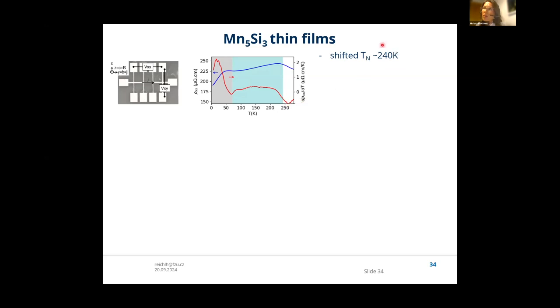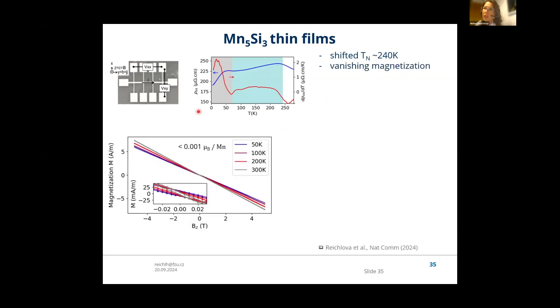So in our case, the Néel temperature is approximately 240 Kelvin, and it's paramagnetic above. In this temperature range, it's a collinear system, and in the low temperature regime, it's non-collinear, and we are not so focused on the low temperature phase, which is rather complicated. We always check the magnetometry.